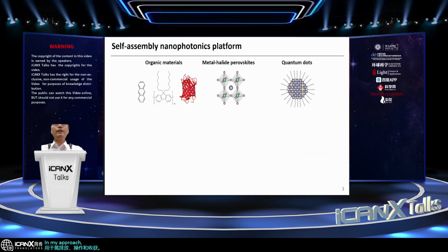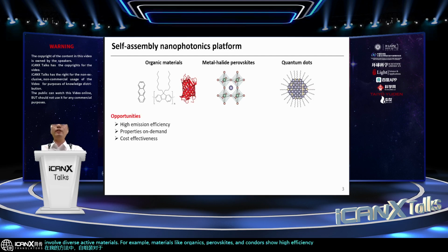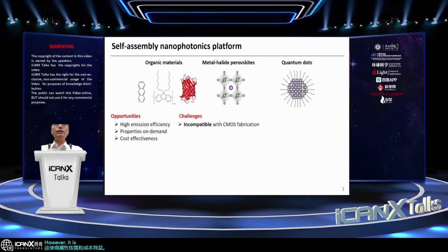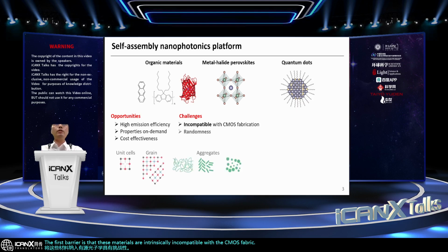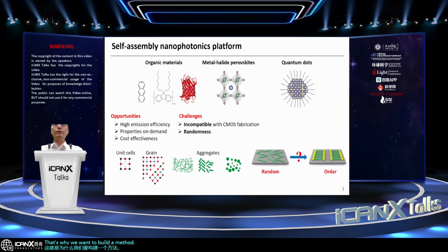In my approach, self-assembly is important to involve diverse active materials. For example, materials like organics, perovskites, and quantum dots show high efficiency for light emission. They also can be designed and fabricated from the bottom up, which enables properties on demand and cost effectiveness. However, it is indeed challenging to involve these materials in active photonics. The first barrier is that these materials are intrinsically incompatible with CMOS fabrication. They also show randomness in different scales. That's why we want to build a method to bridge these materials to ordered photonic structures and devices.